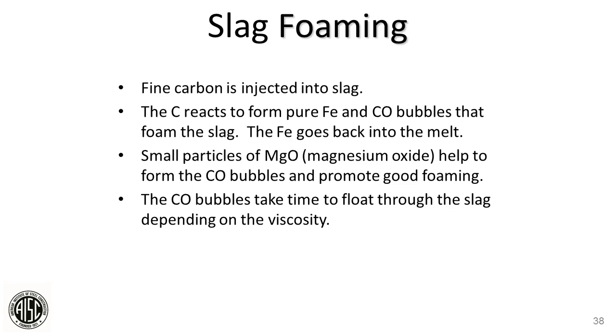So basically, fine carbon is injected through the burners at high velocity. It reacts with the FeO and makes pure Fe and CO bubbles. The Fe goes back into the steel. The CO bubbles up. And the small particles of magnesium oxide, we talked about high-cal and dolomitic lime additions. The dolomitic lime has the MgO, the magnesium oxide, to assist with this process. And they take time to flow through. It depends on the viscosity of the slag. You don't want it too thick, it can't bubble up, or too thin, and the bubbles just pass right through without increasing the surface area of the slag. Next slide, please.